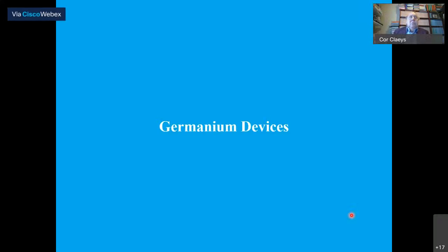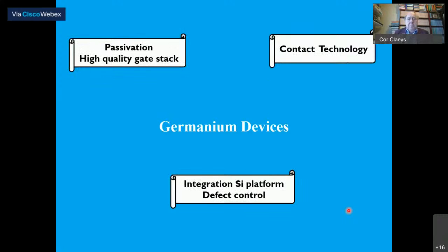Now, in order to improve the drive current, I mentioned already that you can play with high mobility materials. Germanium is one possibility. However, if you work with germanium, there are 3 important challenges. The first one is that you want to have a high quality gate stack. And it's not obvious to put a high K material directly on germanium. You have to do something with the interface. And we call that passivation of the interface. And there are different approaches to do that.